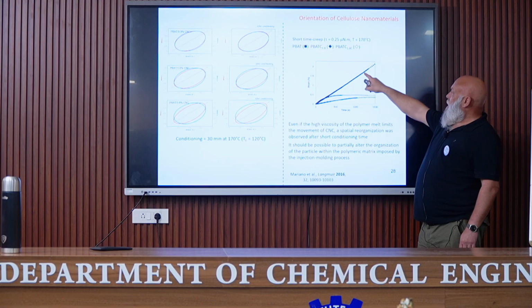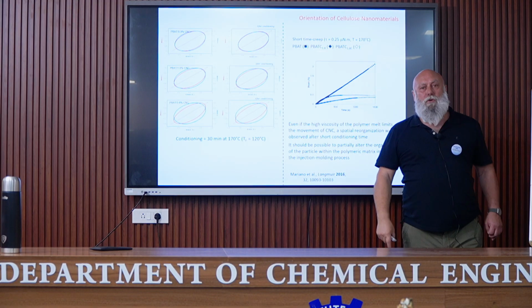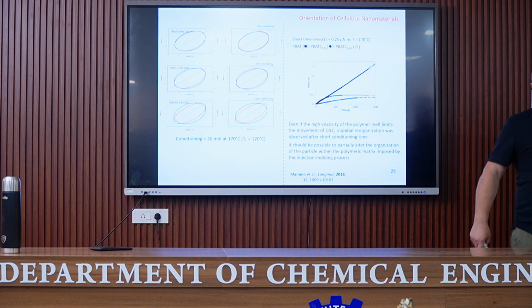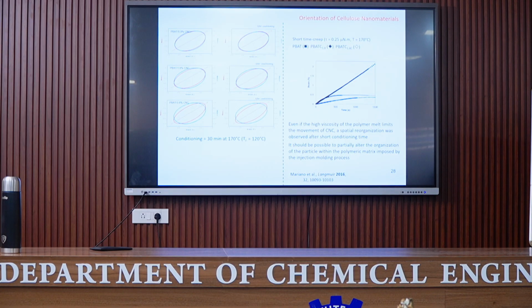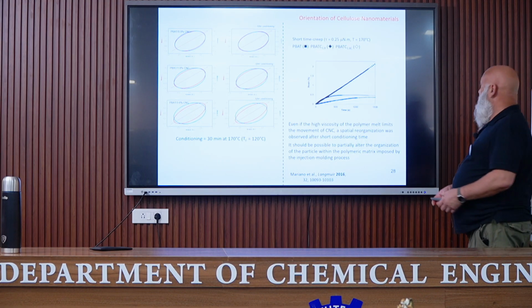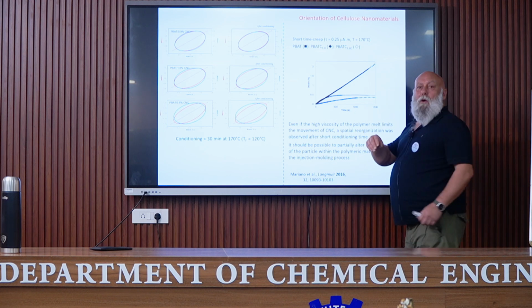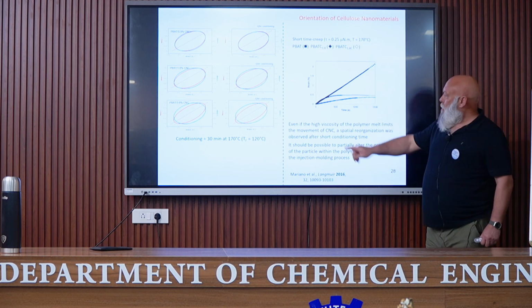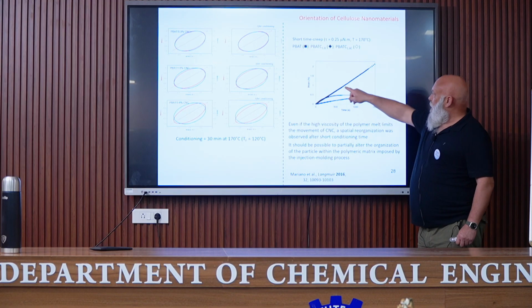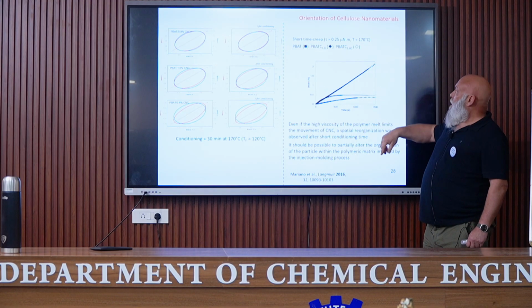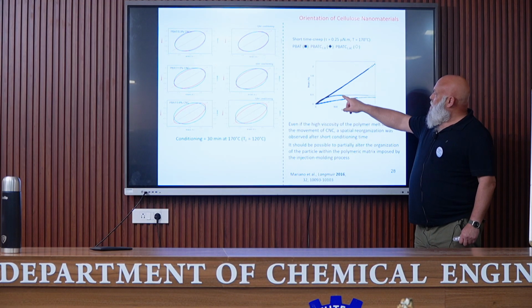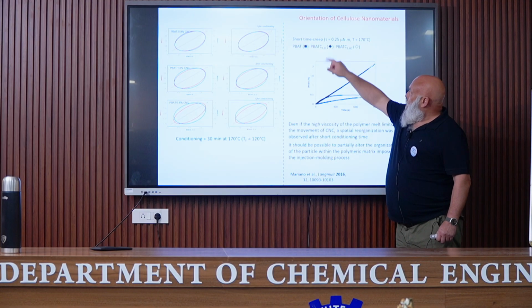For the pure matrix, we have this linear evolution. This linear evolution reveals a liquid-like behavior, which is normal because we are considering a polymer melt. If we consider a perfectly elastic material, we should have a step and then a stabilization. Now for the composite, what we observe is this. So maybe this one.